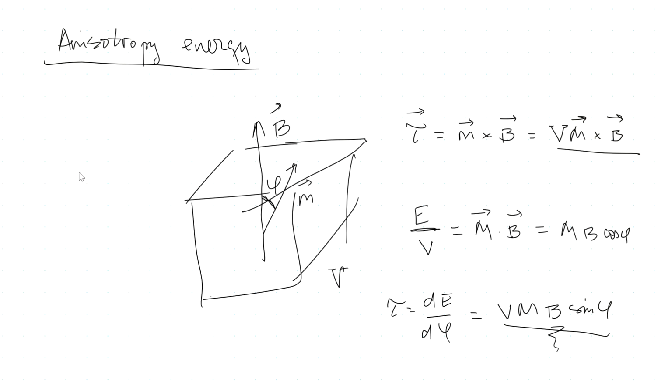Now, if you look at the anisotropy, let's go back to our example with the wire. Our wire wants to be aligned along the wire, so it wants to be magnetized along the wire. If I apply magnetic field this way, then that would apply torque to this magnetization, and eventually it would align itself, but usually it starts precessing.